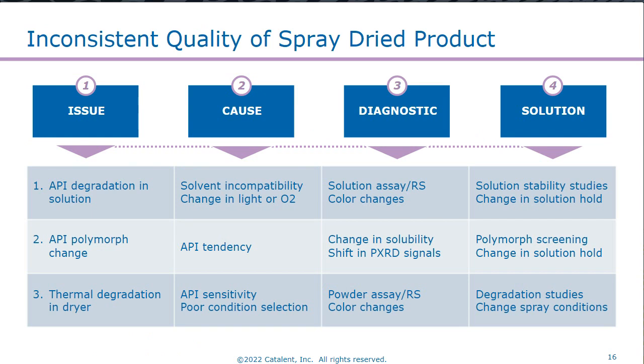Another useful tool during troubleshooting is to create these sorts of troubleshooting guides for project teams and the operations team, where we can have issues, causes, diagnostics, and solutions for these potential issues. So going back to our API degradation and solution example, what are some causes of this? We could have, from early phase, selected a solvent where there is some slight incompatibility with the API. Perhaps our API is sensitive to hydrolysis reactions, and a solvent blend was selected that contains water. This could have been done at early phase because it was the best option we had available at the time to get the solubility we needed, but it does expose the project to the risk of that hydrolysis reaction.